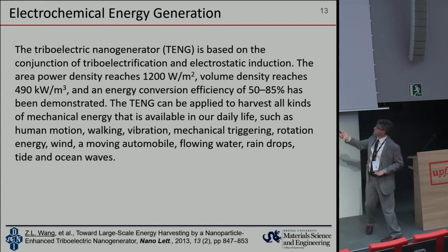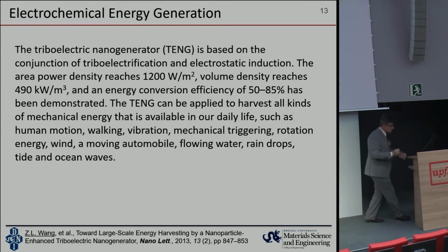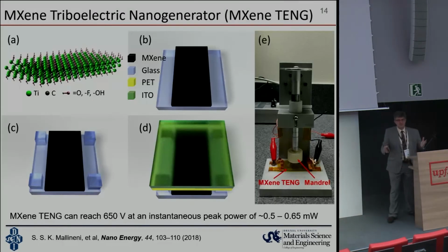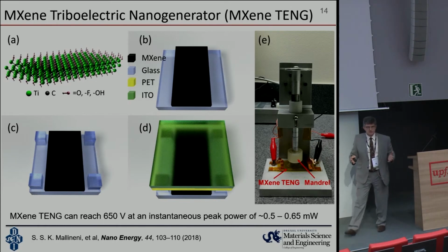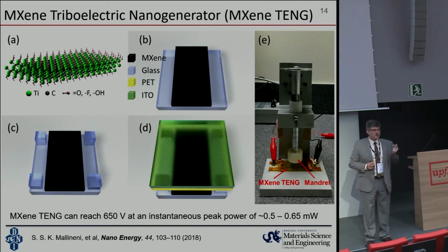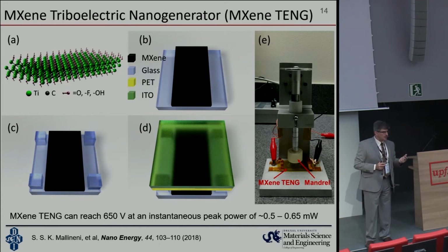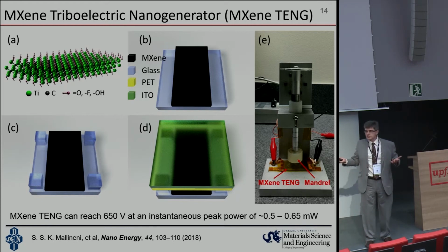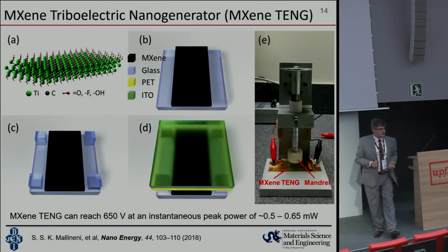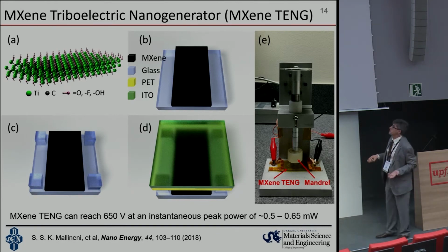And again, there is a lot of effort ongoing here. Why are MXenes potentially interesting here? Because of several reasons. First, as I mentioned, they have a very high metallic conductivity. Second, they can be applied from solution to virtually any surface here, in a very thin film, so that you can even deposit a metal film on surfaces where metal cannot be deposited, and do it at room temperature.